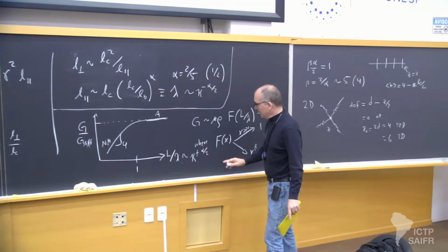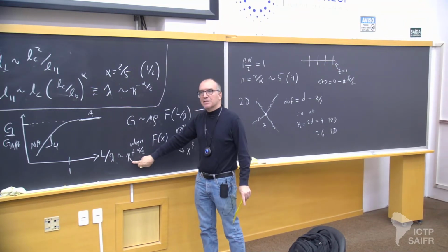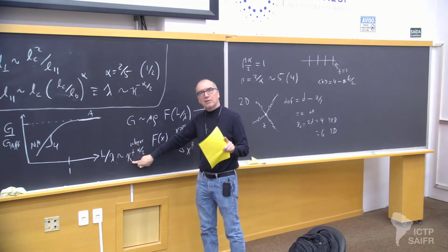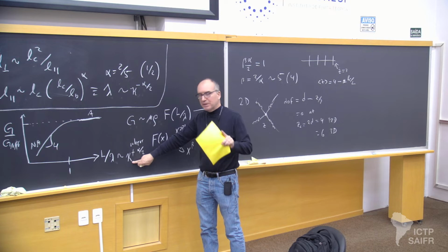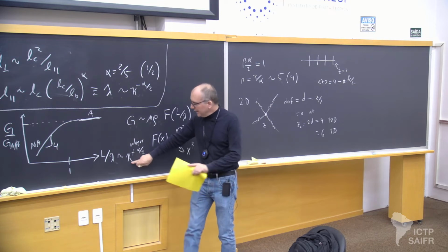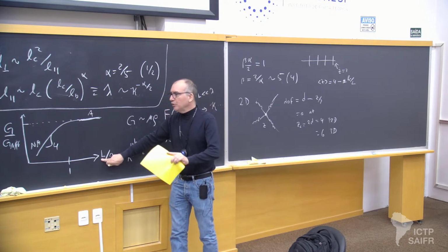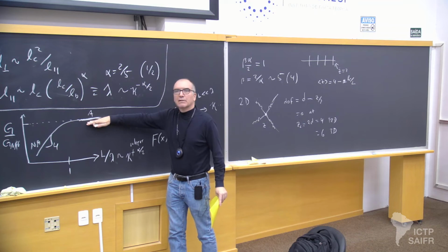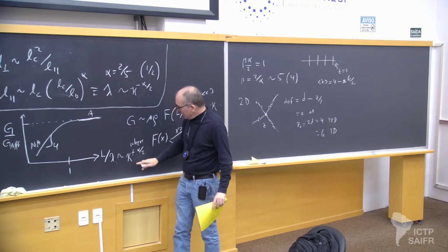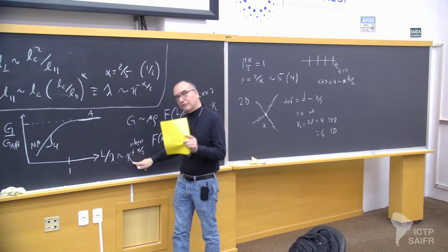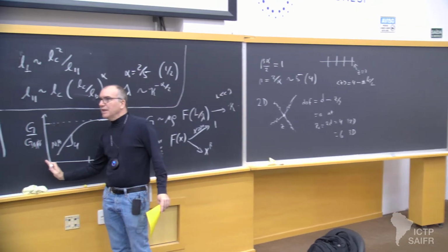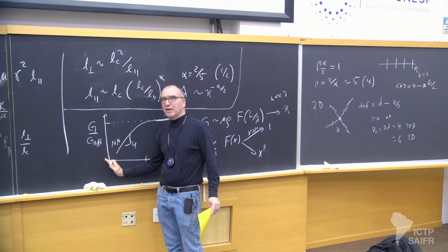What this says is no matter what kappa is, as long as it's non-zero and finite, could be as small as you like, there is a molecular weight beyond which stretching only occurs. It might be a huge length, but it's in principle there. Whereas in the other limit, if I take kappa to 0 first, then I'm over on this left-hand extreme to begin with, and I never move to the right.